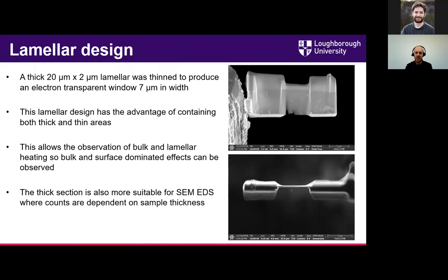So we made quite an unusual shape in a way. We made a sort of dog bone shape. The idea was that we would be able to compare bulk, so thick parts of a sample, to thin parts of a sample, and see how those two areas reacted differently to the temperature applied. We also thought that maybe the thick sample might be better for EDS analysis, whereas the thin sample obviously would be better for TEM analysis.